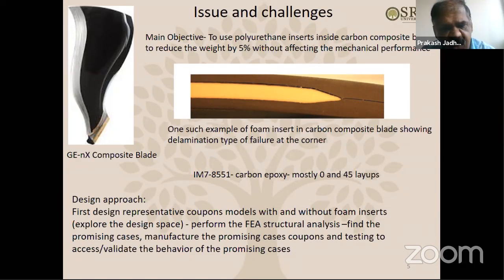Let's design some representative coupon models, with and without foam inserts, these embedded inserts, and then explore the design space, like what different things we can do in those coupons using FEA structural analysis. Based on that, we'll find the promising cases. If you have a certain idea, you can implement it in the coupon models in Abaqus and come up with the promising cases. Only for the promising cases, we will manufacture those coupons and test them under representative boundary conditions and see how they perform. And if the coupons perform better, then we can manufacture a couple of blades for the most promising cases and test them under the test rig.